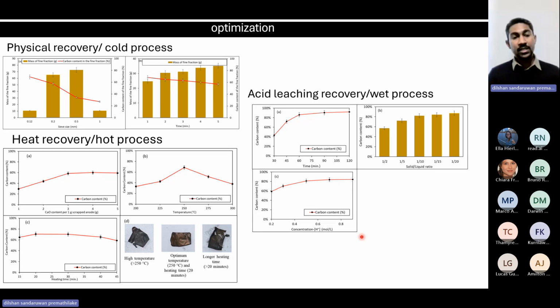So what I did over here was I tried to use calcium oxide along with this anode active material, because the calcium oxide can react with PVDF binders at much lower temperatures, decomposing all the available PVDF material. So here I could achieve complete liberation of graphite at 250 Celsius degrees, which is a great achievement, reducing the comparable amount of heat that I'm going to use for this process.